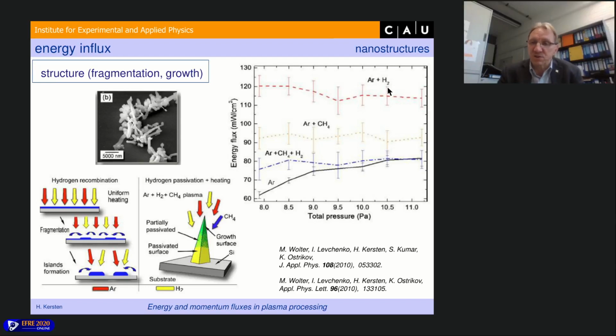The hydrogen is dissociated in the plasma, and the hydrogen atoms recombine at the surface of this nickel layer and heat the surface by this recombination or by this molecule formation. And so you have different energy influxes and different temperatures. And so you can structure this very thin nickel film into nickel dots where you can grow the pillars.